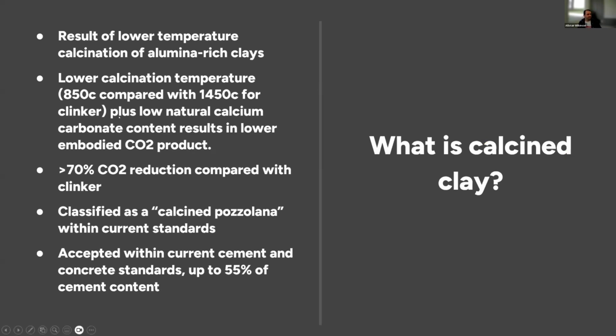So calcined clay is essentially the result of a low temperature calcination of alumina-rich clays. We're looking for components like kaolinite, illite, just clay-rich materials with a lot of alumina. With the lower calcination temperatures, what we're trying to do is remove the structural water and do no more than that. So we're looking at temperatures of 850 degrees compared to 1450 degrees for conventional clinkers. This, combined with having no calcium carbonate in the raw material, means we can really drive that CO2 number down, but create a very reactive cementitious product.